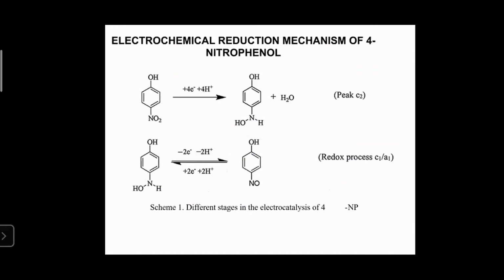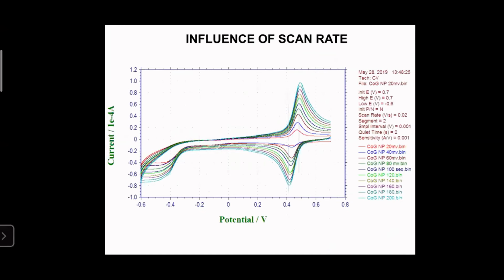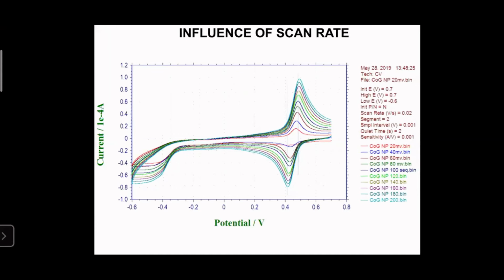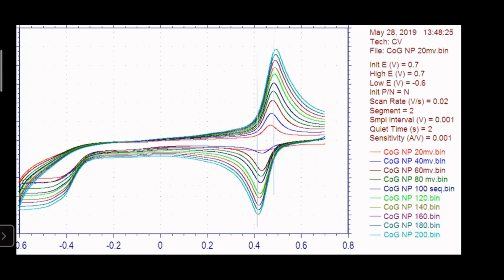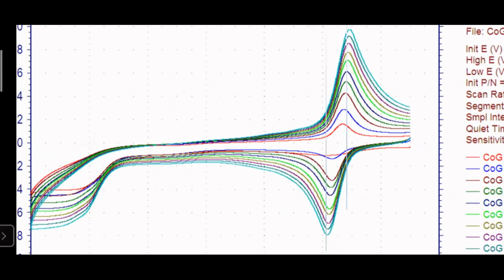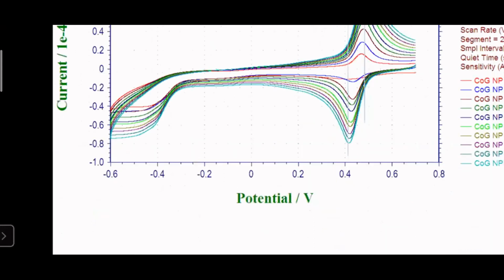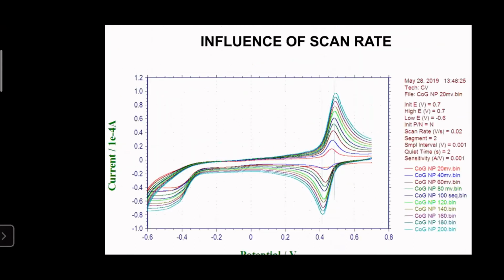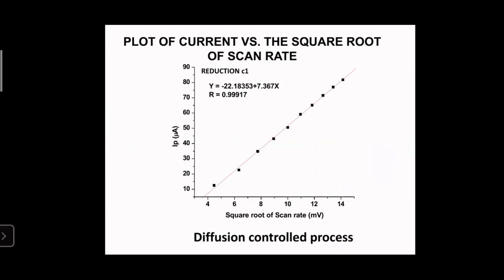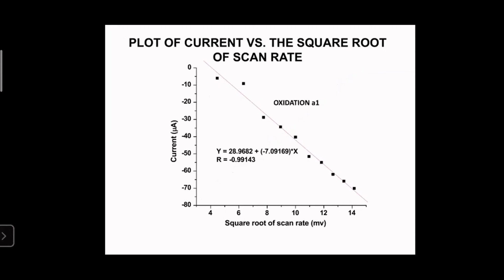In order to study the nature of the electrocatalysis over the cobalt oxide graphene modified glassy carbon electrode, we analyzed the CV at different scan rates. And it can be seen that there is a slight shift of the peak potential towards the right for the oxidation reaction and towards the left for the reduction reaction. This is an indication of the quasi-reversible nature of the process. And in order to check the nature of the electrocatalysis, we plotted current versus square root of scan rate, and we are getting a straight line, and this indicates that the electrocatalysis of 4-nitrophenol over the present nanocomposite is a diffusion controlled process. This is displayed for both oxidation as well as reduction reactions.